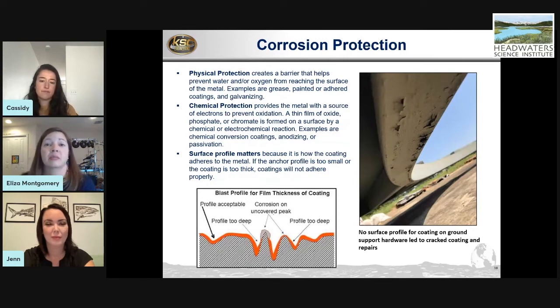And then surface profile really matters. Something you almost never think of, but I don't know if you've ever seen anyone rough up a surface before they paint it. This is really important because it needs something to stick to. Think of it like Velcro, where if your surface profile is too shallow or it's really smooth in many cases, it's just going to fall right off. Same thing for Velcro, if it's really small, it's just going to fall right off. It's not going to work. And if your surface profile is just right, the coating is going to stick. Or if it's too thick and the surface profile is too low, it's going to fall right off too.